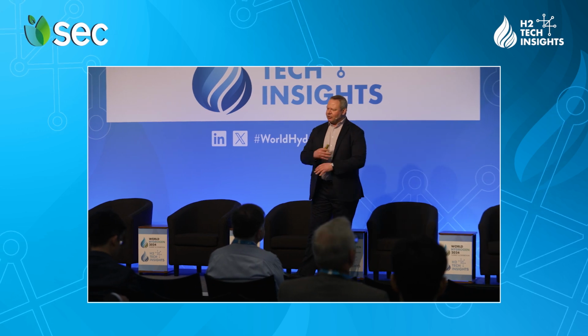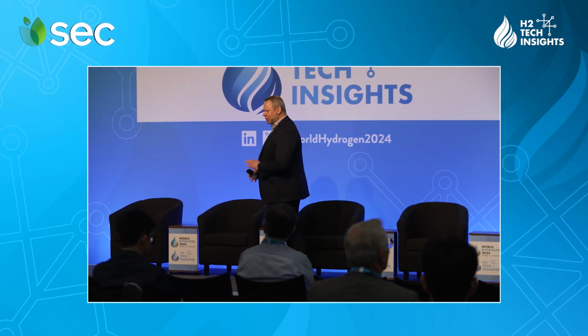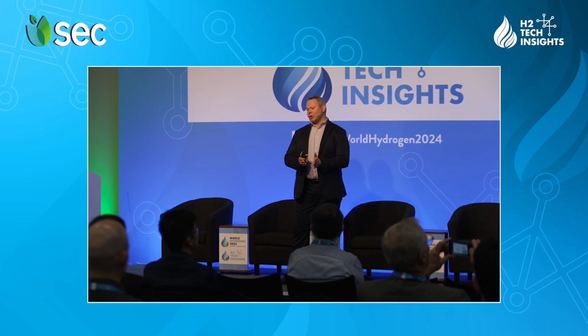And in clean energy, especially when we start to talk about hydrogen, one of the most important components in the entire clean energy space is what's called the porous transport layer. In a PEM water electrolyzer, the porous transport layer is a porous metallic component that is directly adjacent to the anode, which is the electrode that is responsible for oxidizing water, releasing oxygen, and transporting protons across the proton exchange membrane, where they can later be turned into hydrogen, which is the value-add product.